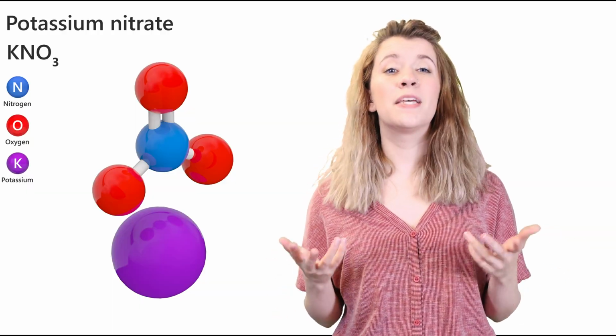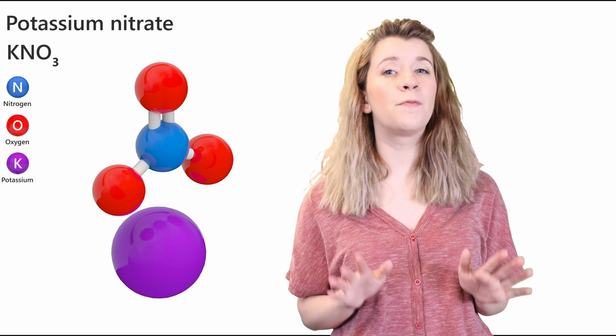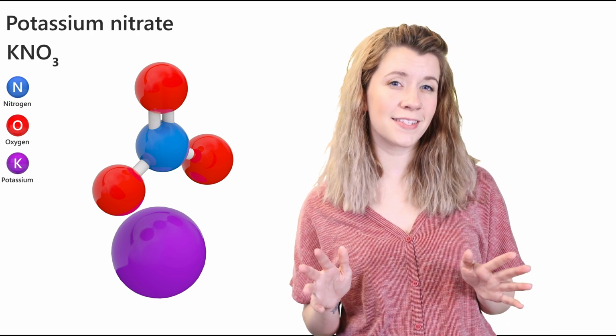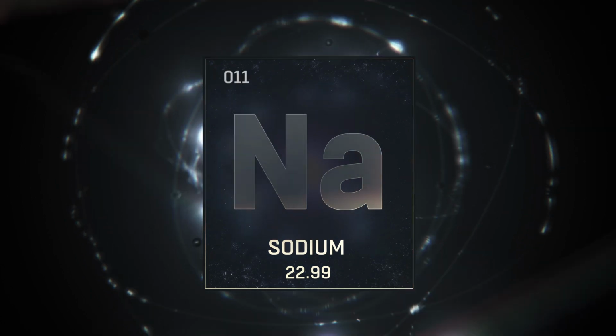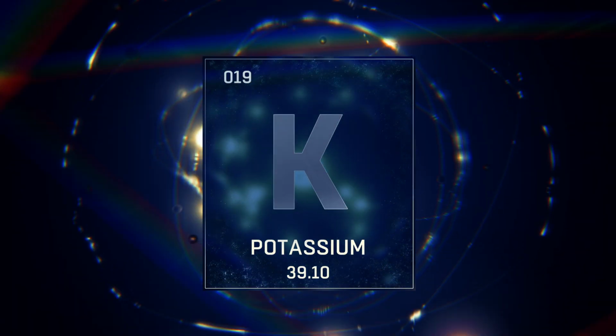This molten salt bath typically consists of potassium nitrate at 450 degrees Celsius. This causes potassium ions to replace the sodium ions in the glass. Potassium ions are larger than sodium ions, so when they squeeze into the gaps in the glass, it makes it stronger. Pretty cool, right? Because the potassium ions are filling in the gaps, the glass is less likely to break.